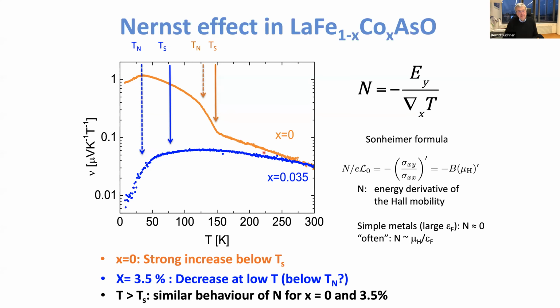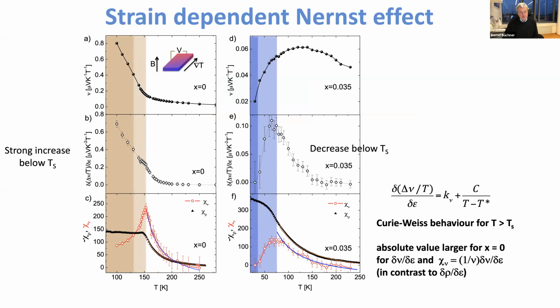And also for the Nernst effect, we can follow this change as a function of strain, which for me was a real surprise. That really tells us that details of this Fermi surface are extremely strongly dependent on details of the lattice. You can determine these susceptibilities if you want, a Nernst susceptibility, Curie-Weiss constants as you see from the resistivity. That's easy. Again, the value for the parent compound is larger than that for the doped compounds.